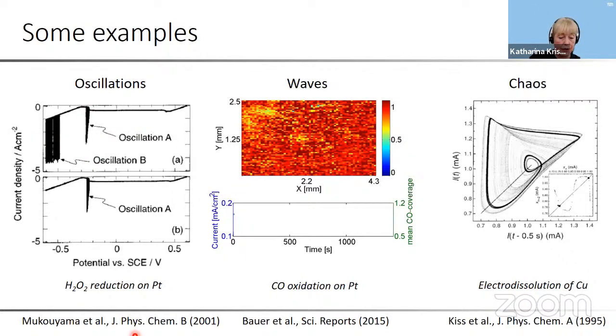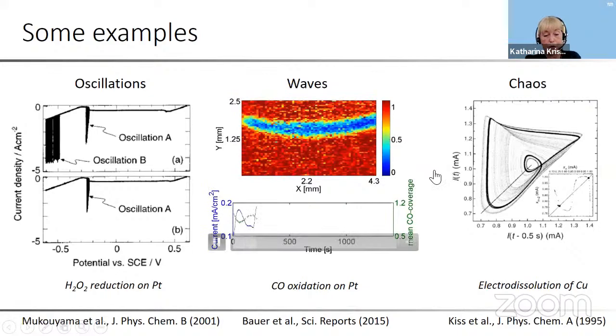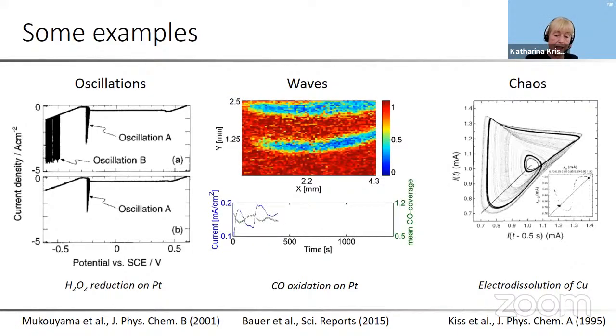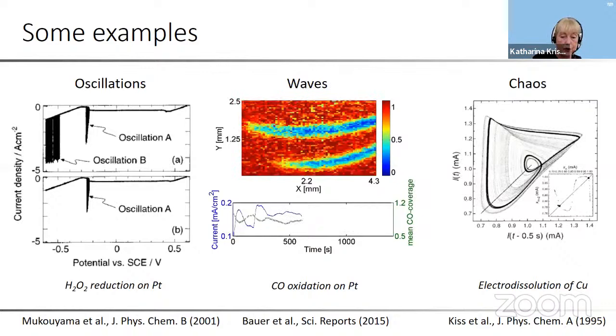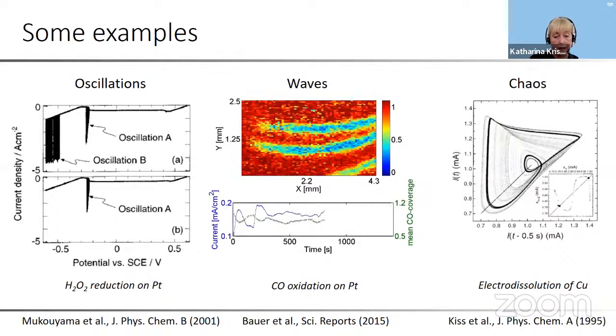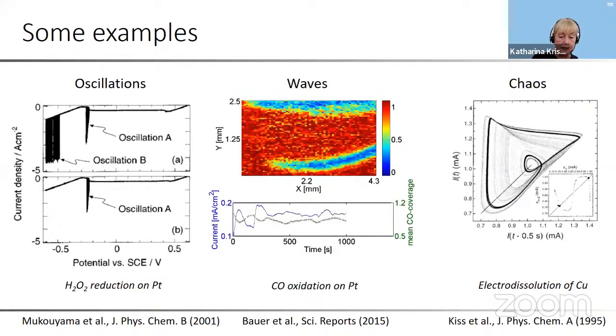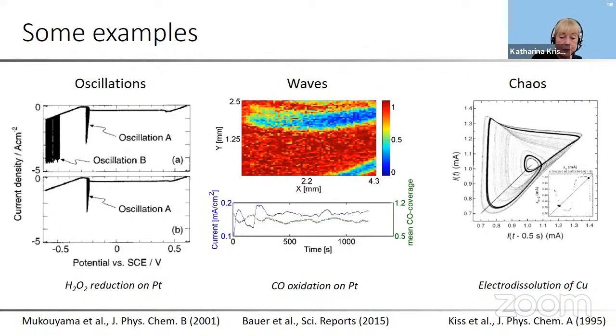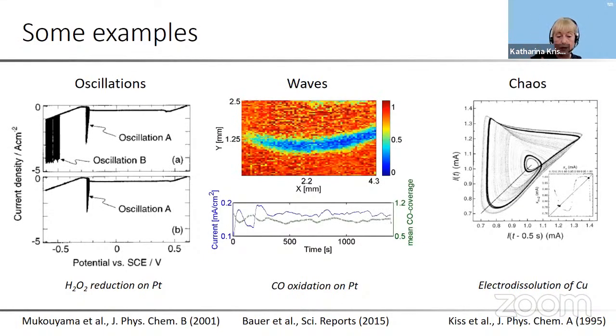Then I show you an example of a wave pattern, which was observed during the CO electrooxidation on a platinum surface. The pseudocolors denote the CO coverage, and you see certain fingers which form on the electrode, travel on the electrode, and can split. These are the reactive parts of the electrode. Everything else is inhibited, so this would be an example of a wave. And here's an example of a chaotic system.